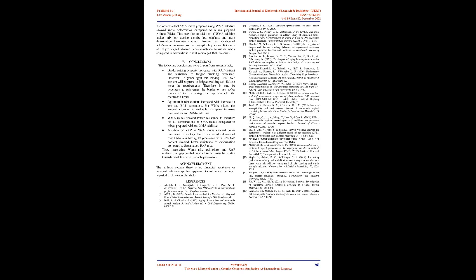From Table 2, the following observations were made. Optimum binder content increases with increase in age of RAP from 5 to 12 years, indicating more bitumen is required to prepare the SMA mix. However, the stability of the mix increased with increase in age of the RAP, indicating better strength of the mix. C. Indirect tensile strength ratio.